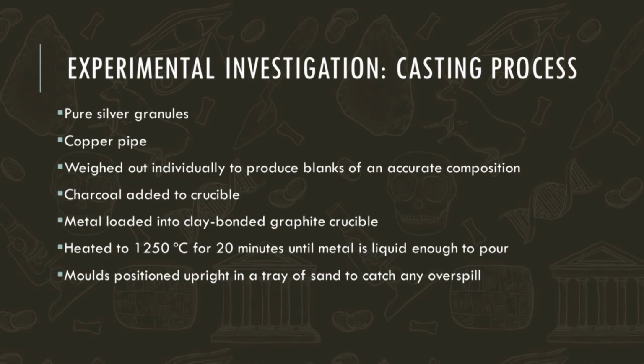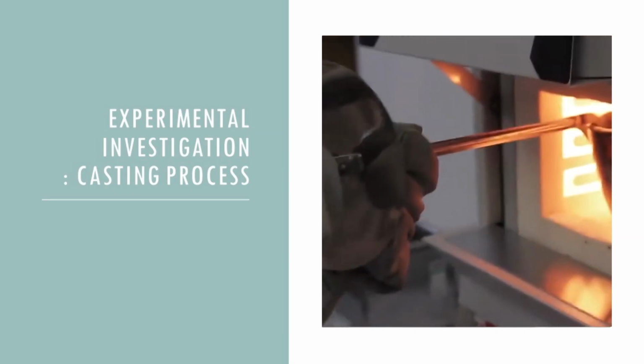So, the casting process. The metals used in all the experiments were pure, so the copper came from copper pipe and the silver used was industrial grade silver granules, and experimental blanks with specific alloy compositions were selected to imitate those found in the ancient coins. A clay graphite crucible was used to melt the metals, and before entering the furnace the metal was covered with a thin layer of powdered charcoal to prevent oxidation. Drawing on previous experiments by Ottaway and Wang, charcoal was also used to dress the moulds before casting. Here is just a short video of the casting process.